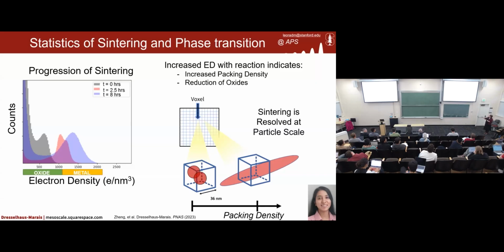We found that there's a cutoff here. So the electron density per voxel here is below a certain value, it has to be an oxide. If it's above a certain value, it has to be a metal. I.e., you could not possibly pack that many electrons into a single space unless you had a metal.